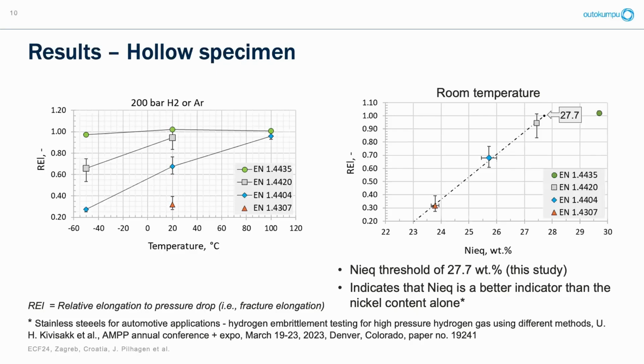And there are other studies that show similar things, so this is in that range. This also indicates that the nickel equivalent is a better indicator than the nickel alone for these grades. And I think the main takeaway here is that it's not enough to just state the grade. You also need to give information about the composition, or the nickel equivalent. For example, for this 44, you can actually buy a steel which has low nickel equivalent or high nickel equivalent. It's the same grade, but they will have different behavior in hydrogen.